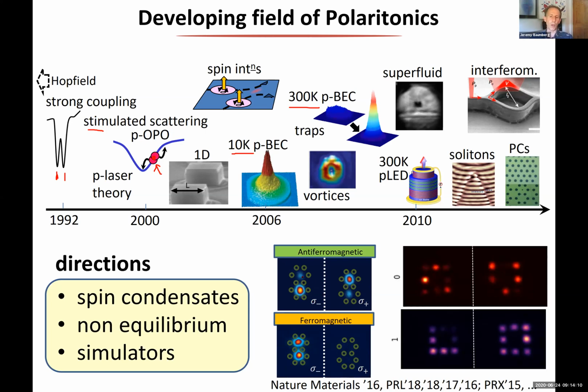So each of these spots here is actually a condensate. And what we found was we could make condensates that were magnetic. So these are either spin up or spin down. What we're doing is resolving these optically. So we can see in circularly polarized light, in sigma plus light, you see spin up condensates, and in sigma minus, you can see spin down condensates.